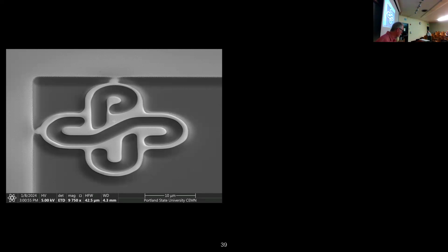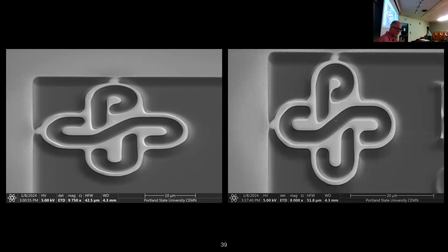Squash. Yeah, it's a little squashed because it's a 52-degree angle, and I didn't have the scan compensation set correctly for this particular imaging mode. I reset it, and then it came out a little bit more square, more like it should be. That's more how it should be. This is the smallest PSU logo as far as I'm aware. It's about 1/3 the diameter of a human hair. I did kind of luck out and get it at 30 microns. That wasn't an intentional choice, but I wanted this to be big enough that I could break my own record later on.